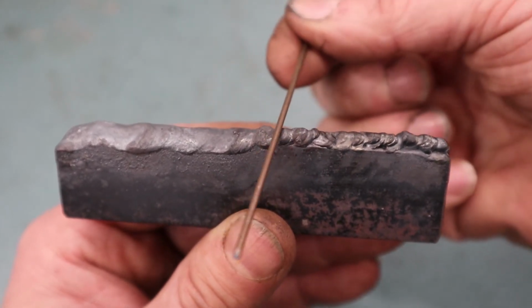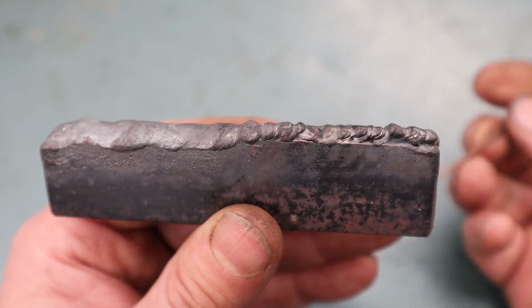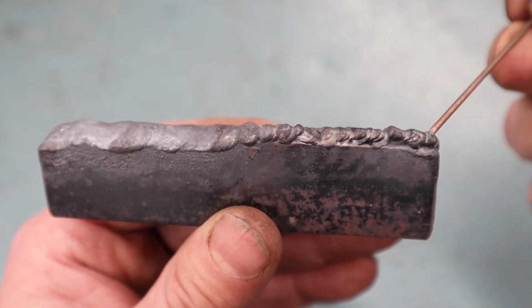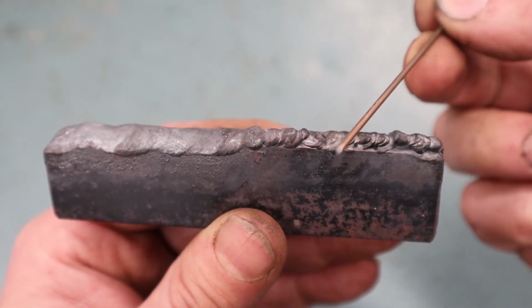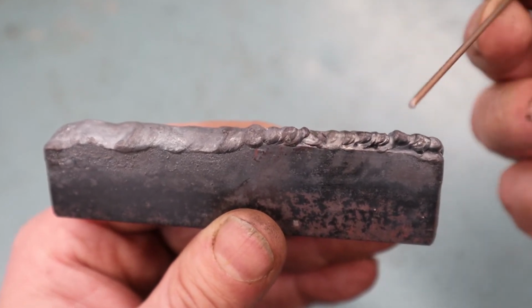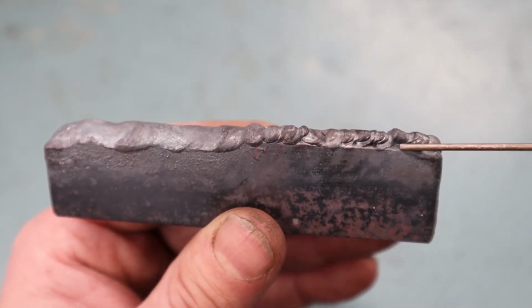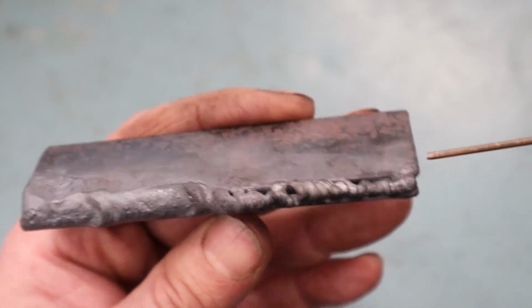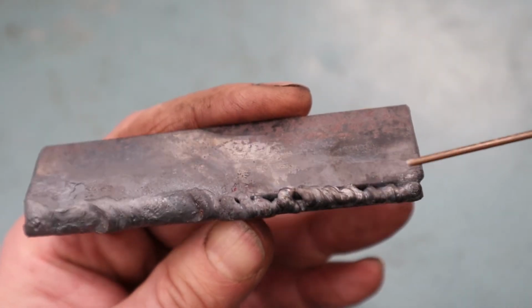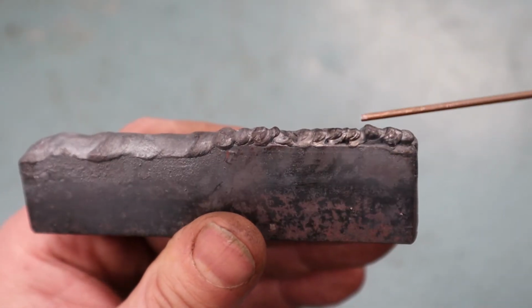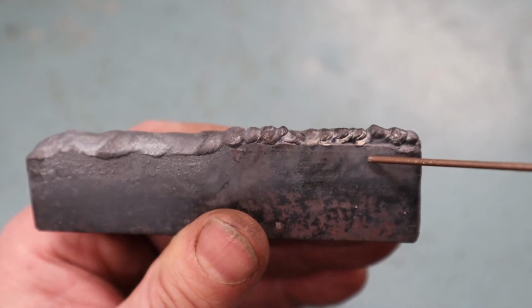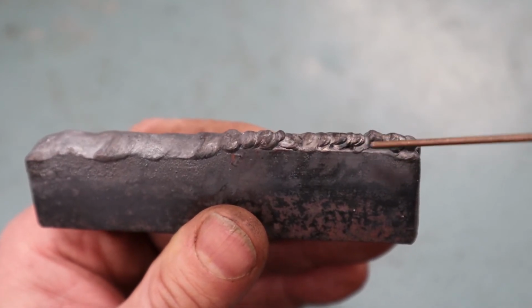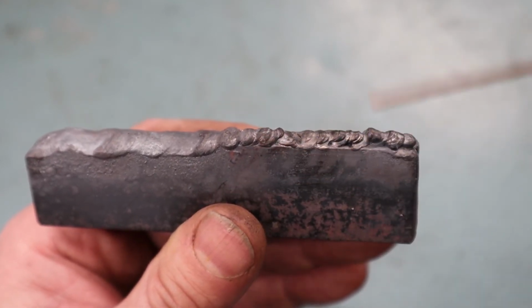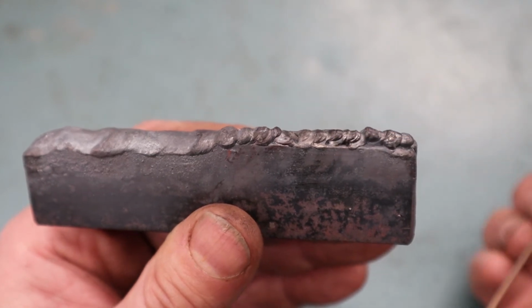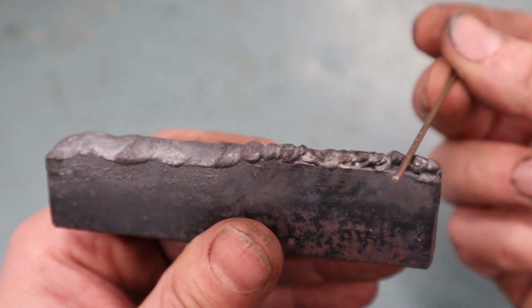Now, this half here is too cold, and it's really obvious because it looks like bird poop. Basically, just big irregular lumps sitting on top of the surface. You can even see the original little spots there of the top surface. It's even worse on this side, and you can tell that it is not melted or fused into the base metal. Lots of little inclusions, so that puddle did not get hot enough to spread out and melt to the next piece. So really obviously too cold on this.